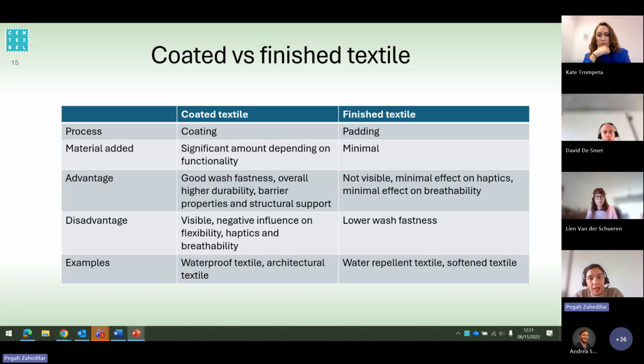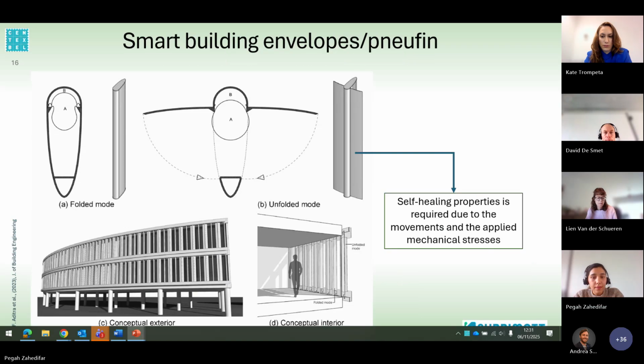On the other hand, if we apply the polyurethane in the form of padding, then we will have the treatment only at the fiber scale instead of the whole area of the textile. Then it will be less visible and have less effect on the properties of the textile, and it will still be breathable, but the stability of this kind of treatment is much lower than the coating. Some of the examples are water repellent textile or softened textiles.